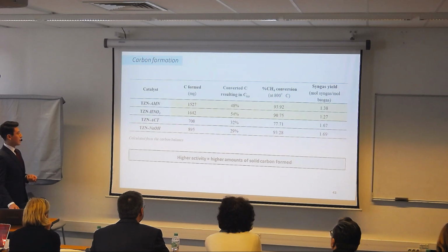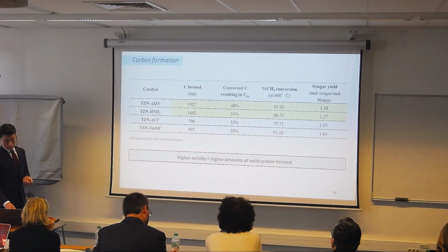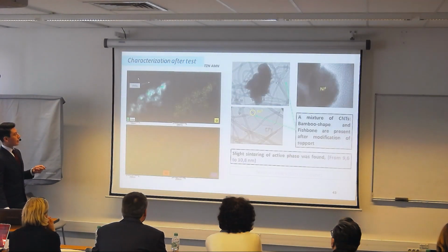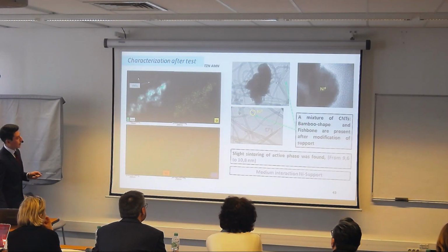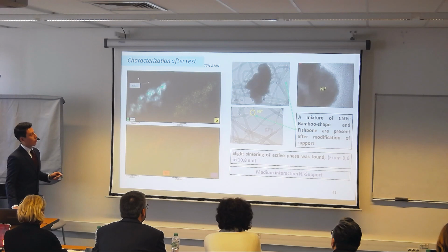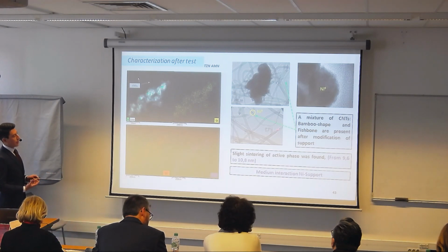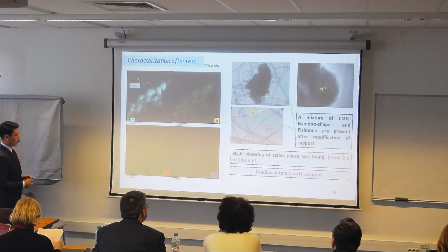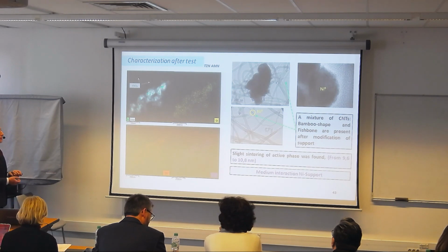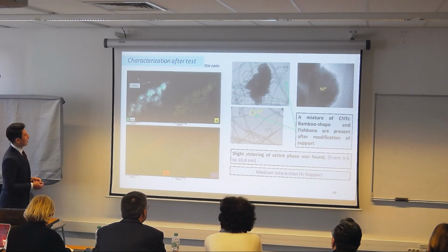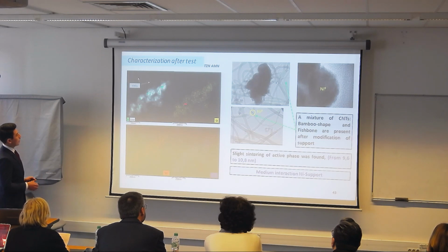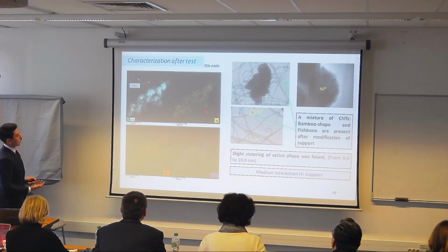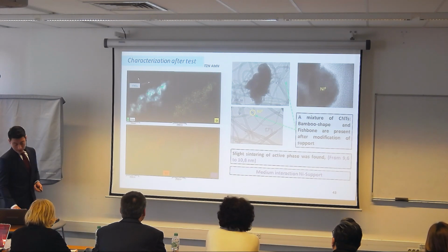Same as before, the higher the activity, the higher the amount of carbon after the test. As you can see here in this TEM, we have very clear nanotubes. However, in this series of catalysts we have a mixture of bamboo-shaped, as I previously showed, and now fishbone carbon nanotubes. We found also a slight sintering of the active phase, and the elemental mapping shows that even after the reaction we have very well distributed phases.